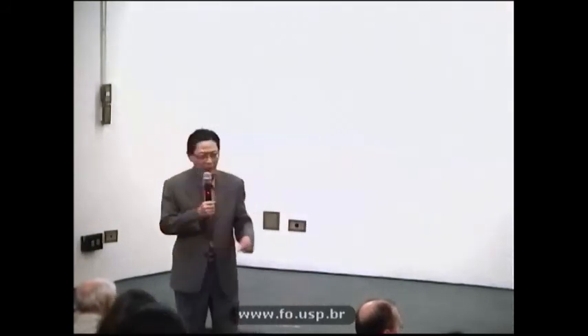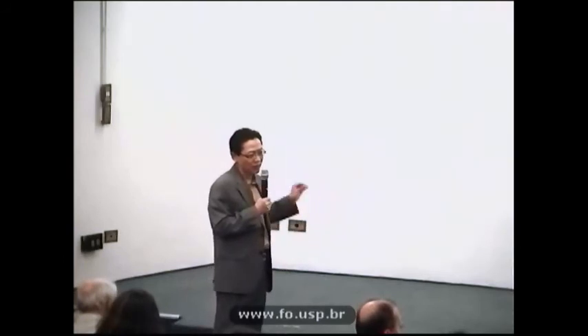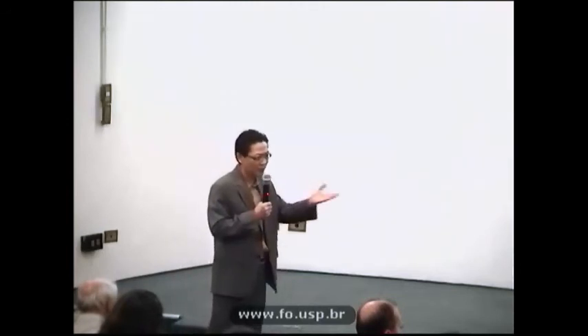Do you think that the contribution of the friction versus the other modes changes when you do the overstress acceleration? Yes. And I didn't show it here, I think I showed it briefly. When you have friction on the surface, the tensile stress at the trailing edge of the moving indenter, if you only have a friction coefficient of 0.25, can boost the tensile stress by a factor of 4. If you get up to 0.5, it's almost 5 to 6 times higher stress. So the material experiences a very high tensile stress if you have high friction on the surface. That's the surface stress analysis. I did it with Brian Lawn.